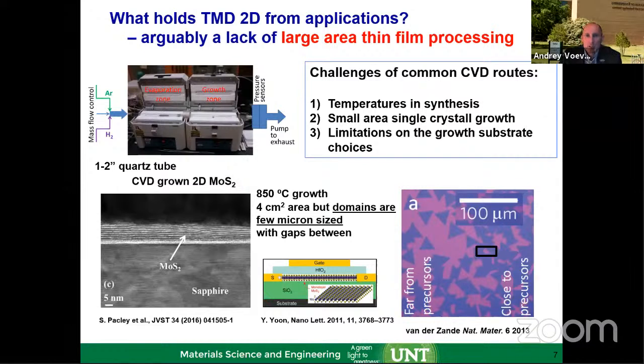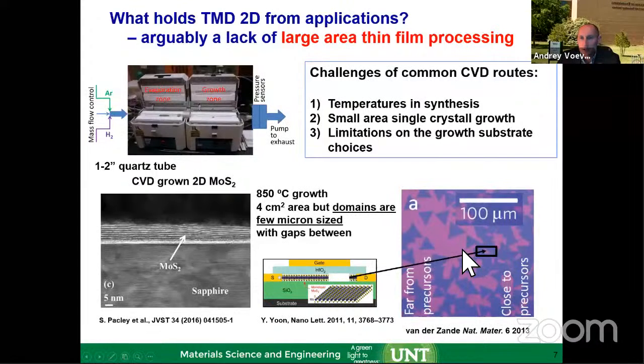But high temperatures lead to crystalline growth, and they grow in this layered formation as shown here, a few-layer-thick molybdenum disulfide on a sapphire substrate. If you look at a planar view, from the top, you will notice that they nucleate and grow as perfect crystals, in this case triangular-shaped crystals, and they pop up and start spreading until they cover the entire surface. Now imagine you try to make a transistor out of this, and if your surface is not completely covered, so that many crystals are not joined, then you can run into a situation where you have a gap in your channel because you happen to be right over here, right? So it's a challenge, how you can do them uniformly. Of course, there's a lot of progress being made in that area, trying to make those crystals larger.